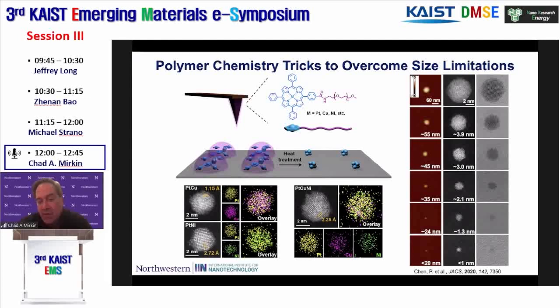What about particle size? And can we get down to particle sizes that matter? I believe that ultimately we're going to be able to get down to single atom control. And this might convince you that we're going to be able to do that. You can't do that with the conventional polymers I talked about because there are many different sites. The pyridine groups are places where the metal ions go, and there are many pyridine groups in each aliquot of polymeric material. And so when you try to reduce the loading, you can get smaller particles, but you begin to get higher variation in particle size.